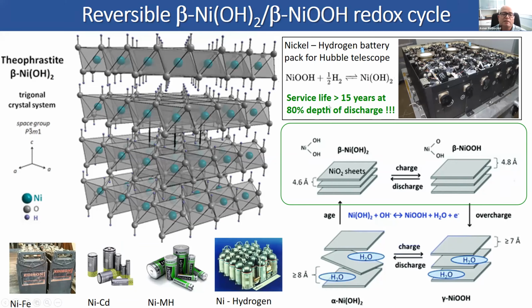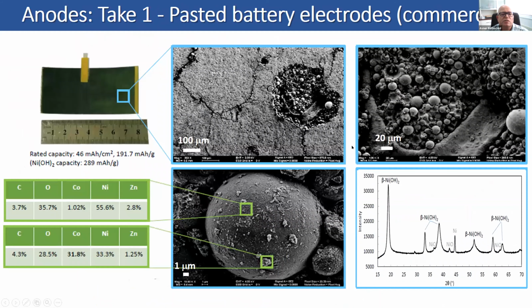And this reaction has nearly 0 volume change. So you see between these 2 phases, they have nearly identical structure, except for this hydrogen occupancy, with nearly zero volume change, and that allows this reaction to be cyclable over tens of thousands of cycles. And indeed, this material has been used in space, batteries that go to space, such as the batteries that go with the Hubble telescope that needs to service many, many years, are based on what's called the nickel hydrogen battery, which essentially does the same electrochemistry, but without oxygen evolution. So that's the reason why we choose this material, because of its long cycle life.